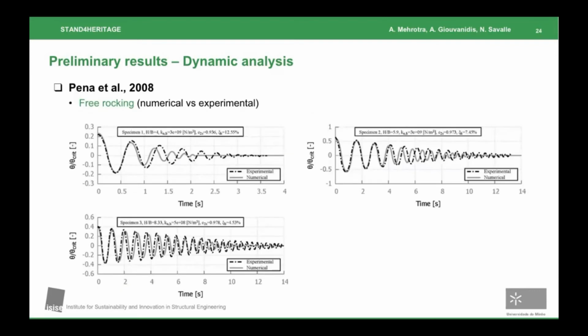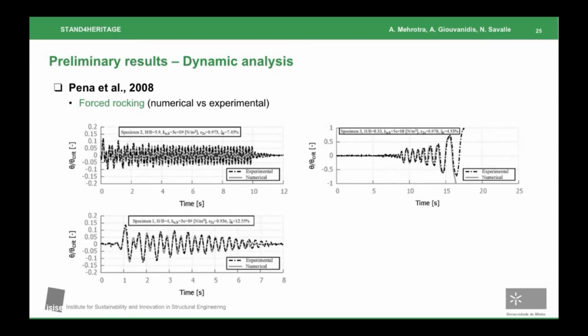From a numerical perspective, the team has focused on reproducing this free rocking response using experimental results from the literature. The dynamic response of rocking blocks with varying aspect ratios was simulated in Abaqus, while an investigation was also conducted into the effect of damping. In addition to free rocking, the blocks were also analyzed for the forced rocking response, and the 2 sets of results were found to compare remarkably well.